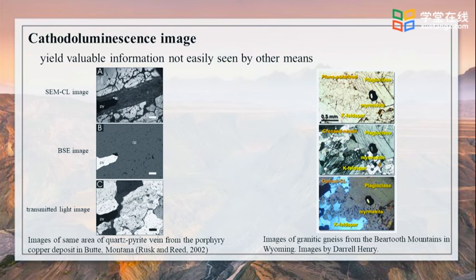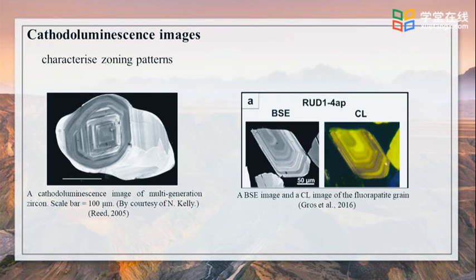For plagioclase and orthoclase, cathodoluminescence images provide a convenient means of identifying these minerals. There are greater compositional variations amongst feldspars, giving rise to a range of CL intensity and color. Cathodoluminescence images of zircon commonly show considerable detail related to growth processes, since the CL emission is at least partly dependent on compositional variations, typically involving rare earths and yttrium.